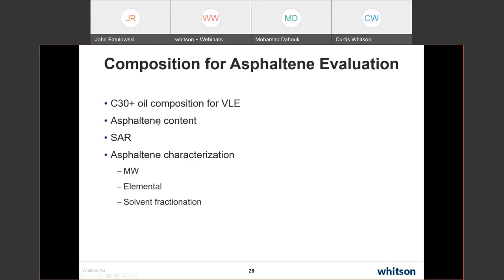SAR, saturated aromatic resin, helps in determining whether the oil phase itself, the maltene phase, is a good or a poor solvent for the asphaltene. And a lot of times this will be measured together. So you'll have SARA data, saturated aromatic resin asphaltene. That'll come as one measurement.